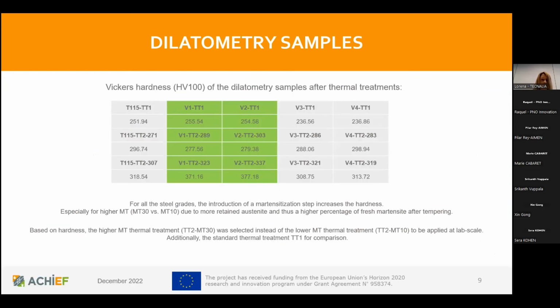Let's see what happens when we measure hardness on the dilatometry samples after thermal treatments. For all the steel grades, the introduction of a martensitization step increases the hardness, and this happens especially for the higher MT temperature, that is MT30 versus MT10, because when we stop at a higher temperature, we are retaining more austenite, and this means that we can obtain more fresh martensite after tempering.